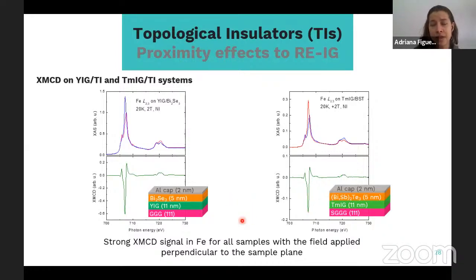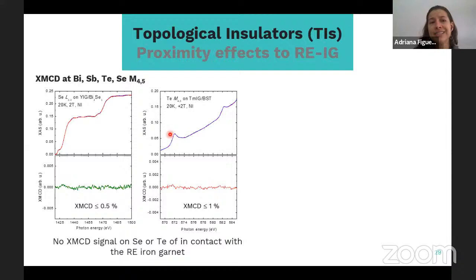synchrotron to perform XMCD, and then to explore first what happens at the iron sites of the garnets, of the iron garnets. And then we observed a strong XMCD signal for all samples at the iron site. But when we go to the TI atoms, again, we see no XMCD signal at these TIs in contact with these iron garnets, not even at low temperature. These are measurements at 20 Kelvin.